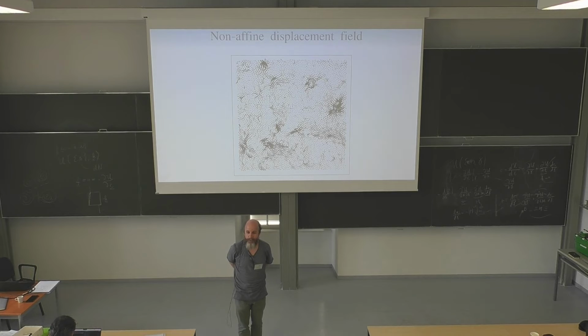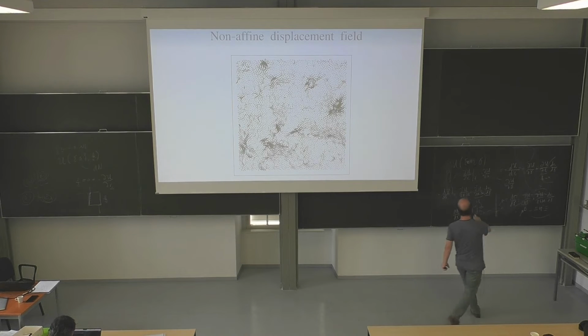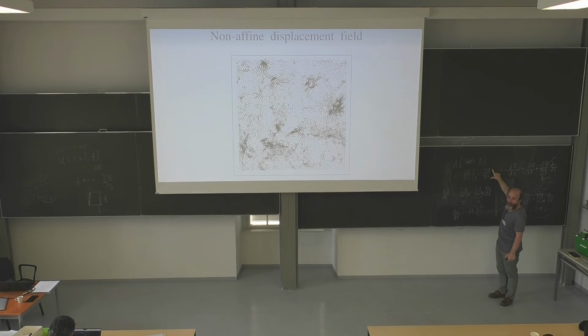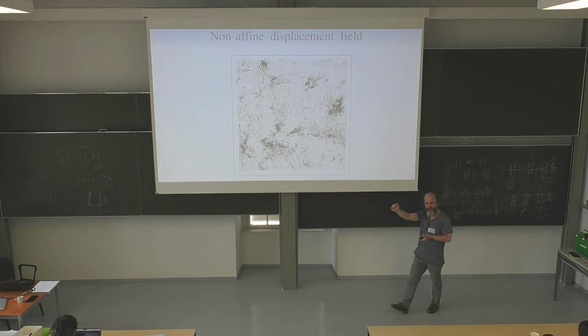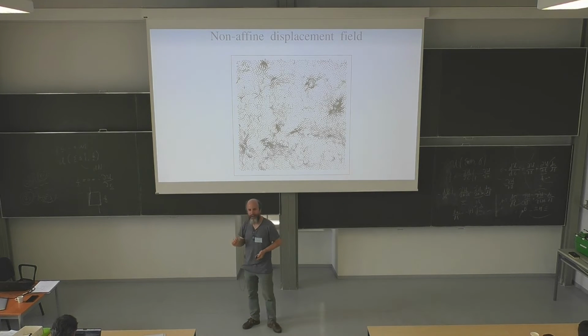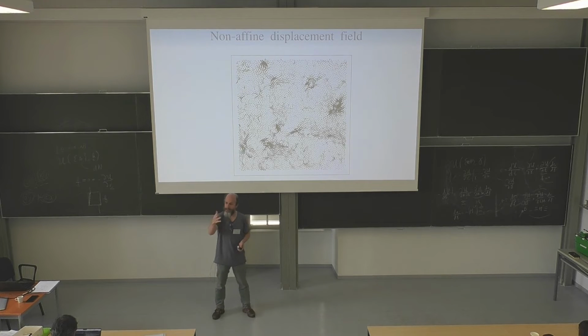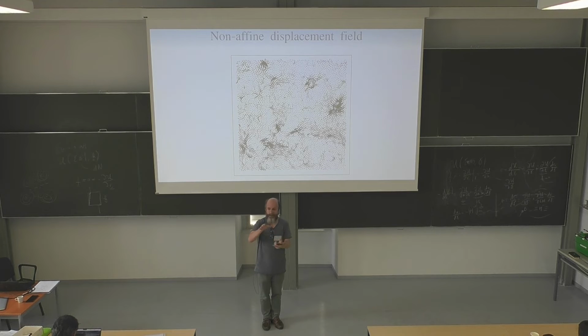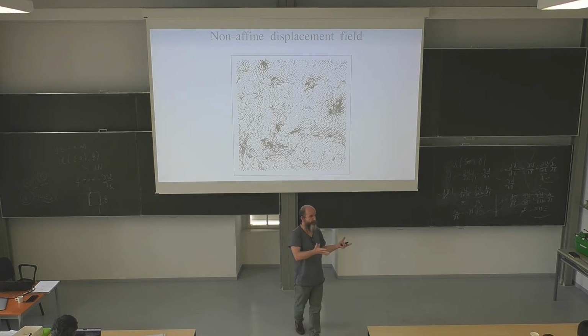Of the stress, yes. You can see this as really the derivative of du/dγ, which, yeah, I prefer to see it as the d/dγ of the force. dF/dγ, which means the change of the force under an affine motion. Otherwise, it's a bit complicated. Yeah, it's really easier to understand like that. So it's d/dγ of the force, and so it's how the force changes during an affine motion. And in a crystal, for example, in a cubic crystal, you can show by symmetry that if you look at the homogeneous response, you don't create forces because of symmetry, and then you don't have non-affinity, right?